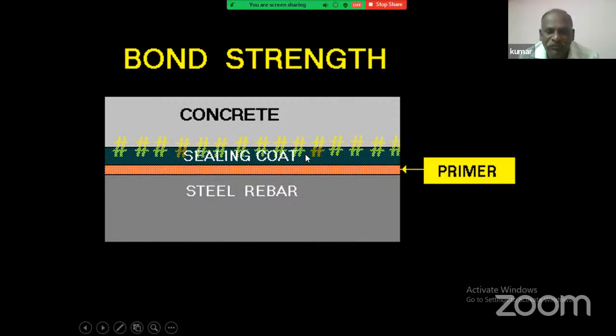But in the sealing coat, we have incorporated reactive cements. So we have treated the cement and incorporated it in such a way that while hydration is happening, that is also hydrating. So because of that, you are getting very good interaction between the coating as well as the concrete. Because of that, it has higher bond strength.